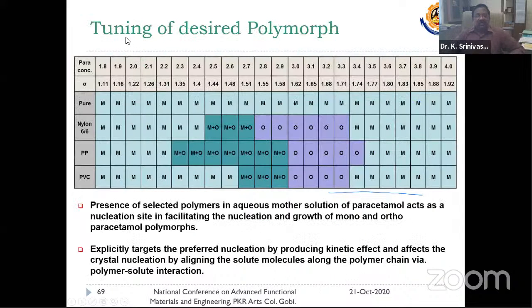Of course, my student did a number of experiments with three different polymers, and this is a pure case with the range of supersaturations and concentrations. Pure solution yielded only the monoclinic, whereas the nylon 6,6 gives mono plus ortho, and PP and PVC, etc. So this region is very, very important to crystallize the form 2. Likewise, one needs a lot of patience and to do n number of experiments with varying parameters to map the crystallization procedures of this material.